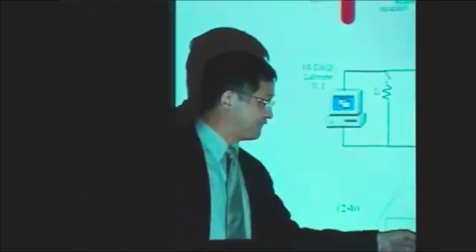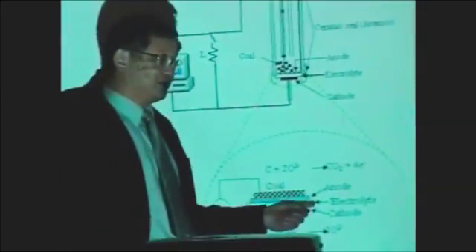After a number of studies, we found a number of very good oxidation catalysts that can serve as catalysts for electrochemical oxidation. There's a difference between an electrochemical oxidation catalyst and a regular oxidation catalyst. A regular oxidation catalyst can be a metal oxide. In the electrochemical oxidation catalyst, the catalyst must possess electrical conductivity. The reason is that once this oxygen anion oxidizes the fuel to generate an electron, the electron must be able to push out to the external circuit. So the catalyst must be electrically conductive.